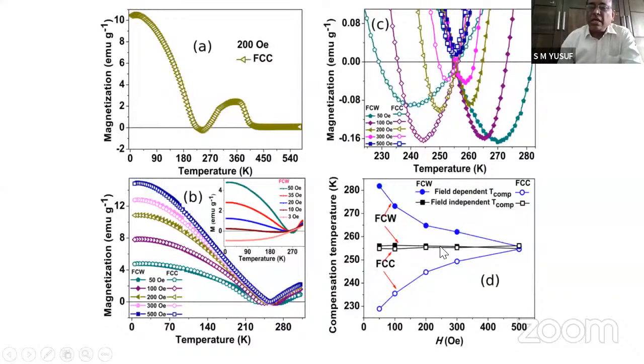And that is also constant whether you do the measurement in field cool cooling or field cool warming. So this particular one. But the other one changes its position, whether it is the field cool warming cycle or the field cool cooling cycle, and that is also field dependent, but at relatively higher field, typically 500 oersted, where the Zeeman energy is able to suppress or overcome the internal anisotropy, then these also merge, all three merge. In fact, all four merge. So this kind of fine observation is possible by doing very careful studies, and that's why I'm saying one has to be very careful when one does the measurement to understand this kind of complex magnetic behavior.